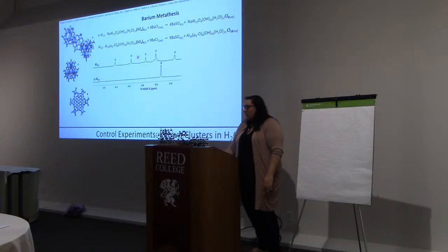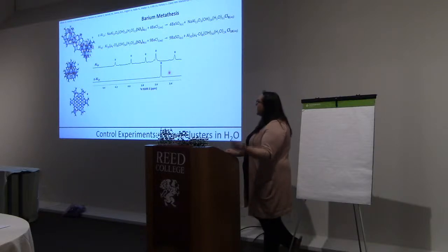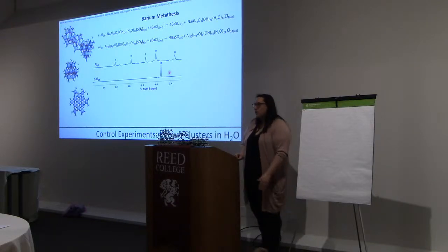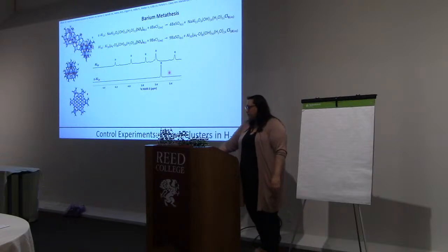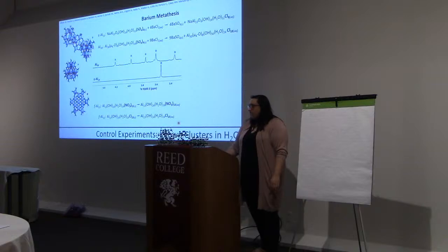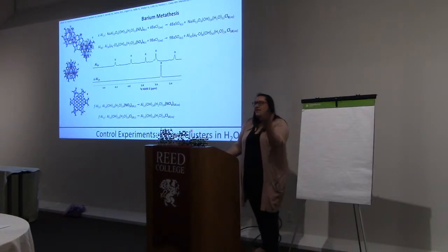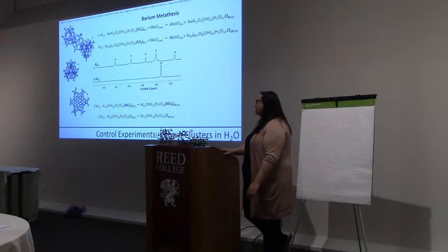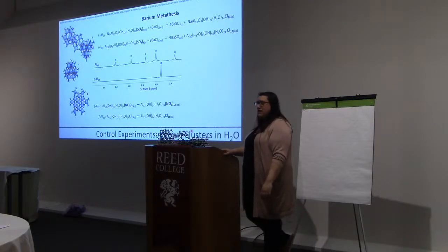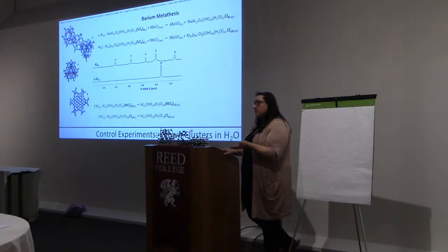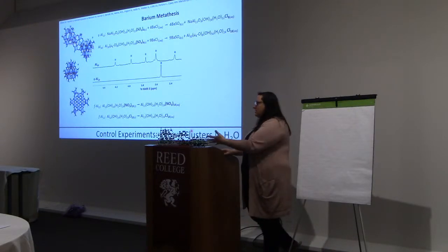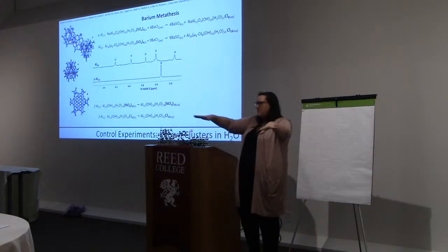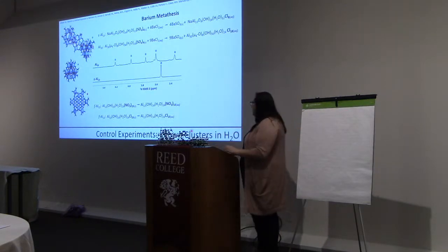And so after doing that, we were able to get very nice proton NMRs after our solvent suppression that gave us those unique fingerprints that we're using right now to identify which cluster is in solution. Now, our flat cluster, when we dissolve that, it has nitrate or chloride counterions, and that just dissolves nicely. You can dissolve these 2-3 molar in concentration, very strong, which is why they made such good precursors for those thin films. You get a really concentrated aluminum hydroxide solution that's already in the shape to build that extended network. That's why it was working so great.